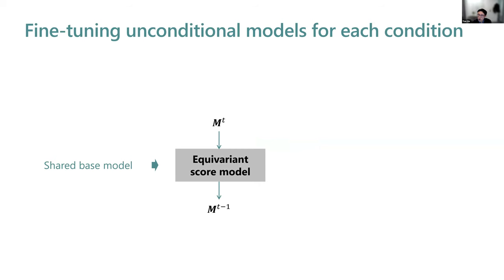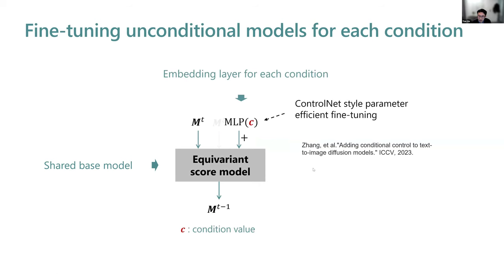This is why we adopt fine-tuning as the main approach to obtain a conditional model from the unconditional model. We fine-tune the unconditional model for each condition that we're interested in. We have this shared base model, which is the unconditional model, and then we fine-tune it for a different condition, where for each condition we have an additional MLP that introduces an embedding layer for each of these different conditions. This component is shared for all the models and this MLP is only for each condition. Here we use ControlNet, which is a so-called parameter-efficient fine-tuning approach, where you initialize the weights and the bias for this MLP as zero. Therefore, at the beginning it doesn't alter the output, but as you fine-tune, it will change the output of this model based on each condition. And that's how we obtain a conditional model from the unconditional model.